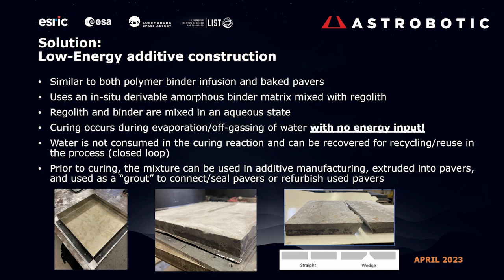What's critical is the curing of the amorphous binder matrix is facilitated by the evaporation of the water, and the water is not consumed in the process, unlike terrestrial concrete. So when we cast or lay out or form whatever we're going to make out of this material, we're able to completely recollect the water and keep the water as a closed loop aspect of the system. Obviously everyone knows the value of lunar water, and we don't want to just be throwing that away. So we've been able to develop a system where we're using water as one of the attributes, but it's closed loop.